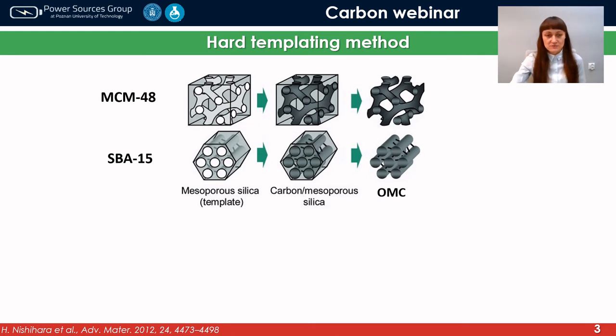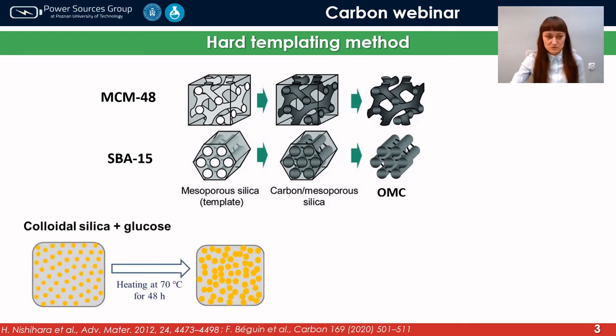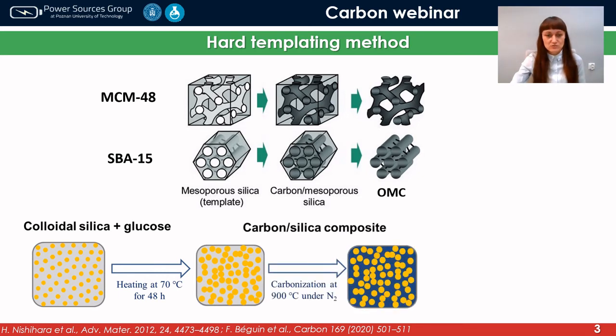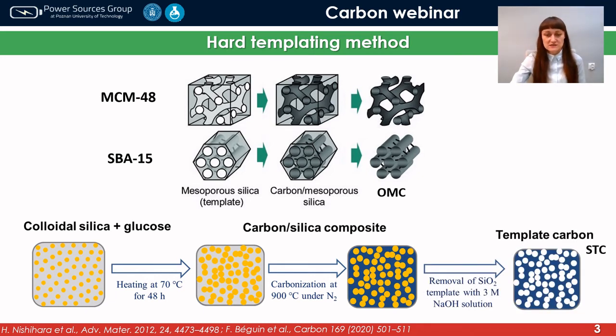And we adapted this synthesis to our purpose, in which we mixed the colloidal silica with glucose, after that heated it at 70 degrees Celsius, and then carbonized it at 900 degrees Celsius under nitrogen flow. And of course, at the end, we remove the silica template with a 3 molar solution of sodium hydroxide. In this case, we are able to obtain the templated carbons labeled as STC, which means silica template carbons.